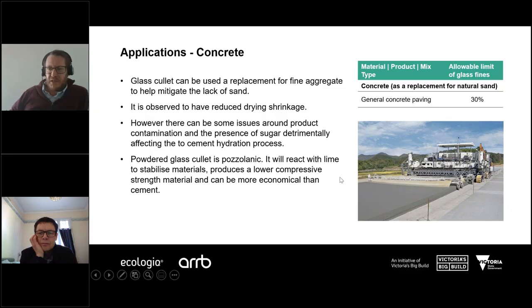So if we were to consider the amount of recycled crushed glass that we could put into general concrete paving, at the moment in Victoria we're allowed to use or replace up to 30% of the fine aggregate with glass fines.